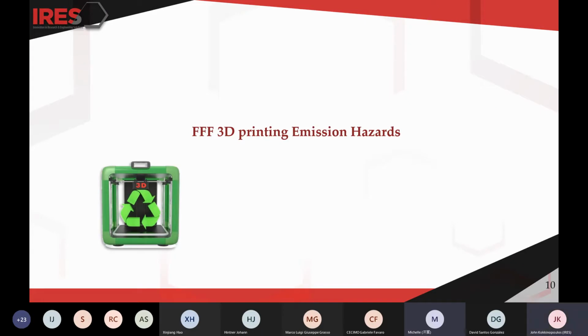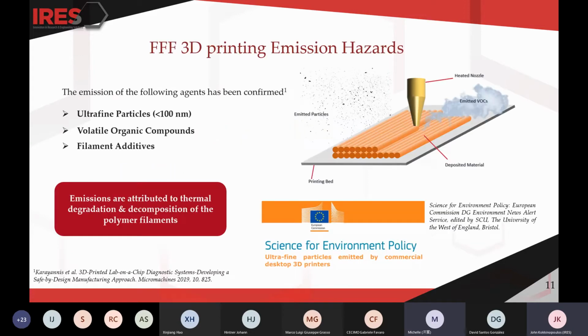In fused filament fabrication, a solid thermoplastic filament is deposited through a moving nozzle heated close to the filament's melting point, as you can see in the next slide. The hazards attributed to fused filament fabrication mainly regard hazardous emissions caused by thermal degradation and decomposition of the polymer filaments. These emissions include ultrafine particles, particles that are smaller than 100 nanometers, which are emitted in significant numbers during the printing procedure. Their increased specific surface area and lung penetration potential can lead to a multitude of health issues as a result of exposure.